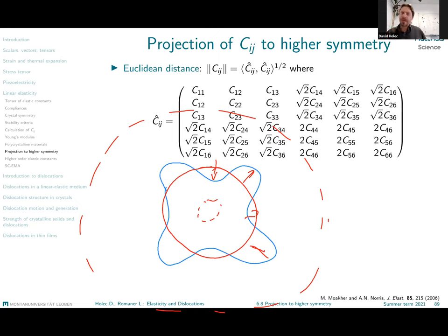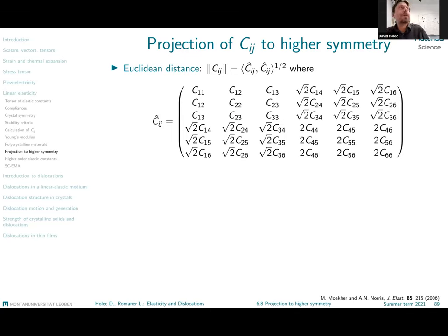which would everywhere hugely overestimate or hugely underestimate the response. And to calculate this tensor of elastic constants with a desired symmetry is done by so-called projection of the elastic constants on higher symmetry. There is one more reason for doing that. For those of you who have ever tried to calculate elastic constants with the stress-strain method, you probably have realized that what you get out of the calculation with this pseudo inverse has nothing to do with the desired crystal symmetry. Again, due to the numerical inaccuracies.